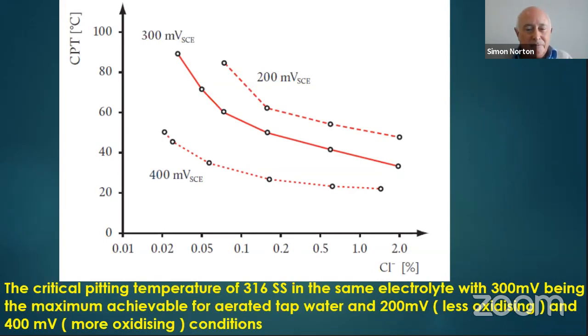In this particular case, in the center, we have 316 stainless steel in aerated tap water. And for instance, if we have 1% chloride in the solution, then we're going to have a critical pitting temperature of just over 40 degrees centigrade. But if we only have 0.1%, we're going to have a critical pitting temperature much higher at that particular open circuit potential. So while you do not have to understand the detail of what I'm showing you here, the point I'm trying to make is that critical pitting temperature is a very useful design parameter.